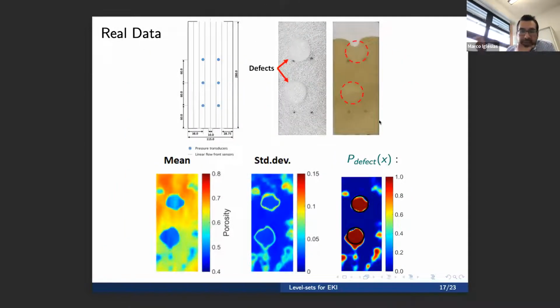Now for real data, exactly the same setting, exactly the same geometry, except that instead of simulated data, our colleagues manufactured this composite part where they put some circular defects in the same area that we used for the synthetic experiment, and they lowered the porosity there somehow, and then they infused the resin, and they gave us real data from the pressure transducers and the flow front sensors, and then we applied the same technique with the same prior. And what we got is very encouraging results given that it's real data, and that involves inferring the two regions of low porosity that they engineered, and the standard deviation reveals high uncertainty in areas where there was not supposed to be a defect, and we can compute the probability map.